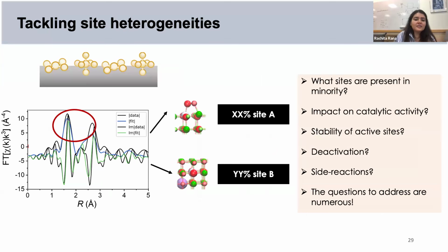So you're really looking at the majority of sites that you have. But if you can get to this, the benefit of using these atomically dispersed catalysts is that you can really get to the minority of species that could be present. And those minority of species can be very important because they could be the active sites, and your bulk species could just be spectators in a catalytic reaction. So you really want to understand what is leading to your active sites.